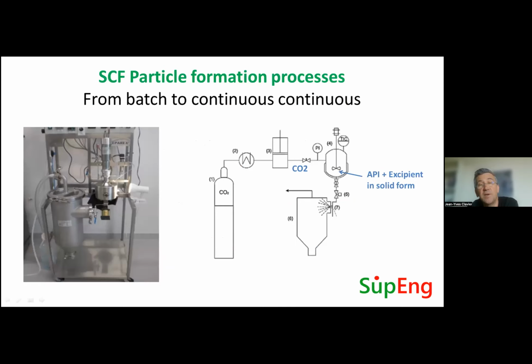When you have an active principle, it can be a protein that you want to protect with an excipient. It can be a flavor that you want to control the dissipation. So you have several fragile molecules that you want to control the delivery and that you want to protect with an excipient. Basically, you have a mixed reactor where you are mixing all this under pressure with CO2, and then you spray it in an atomization vessel. This is a bit complex because you have to master the mixing condition, and it's very difficult to control the transfer from a high pressure condition to a low pressure condition when you don't control the quantities. You control the initial quantities, but you don't control right after you open the valve in this batch vessel. So using this in a batch mode is quite complex.